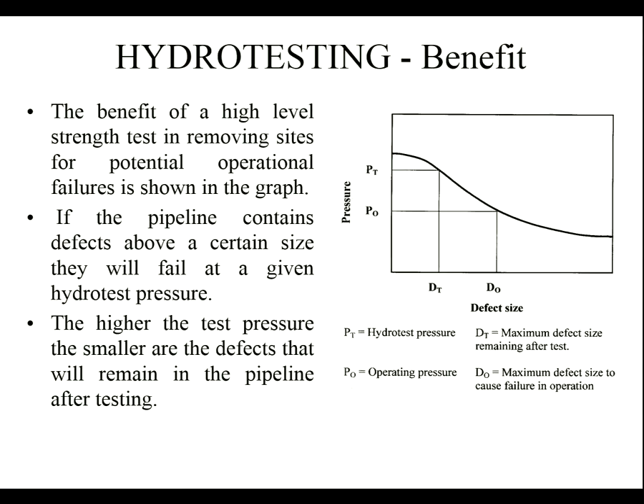And this graph, if you could see all of it, shows the pressure of failure against defect size, and you can see as the defects get bigger, the pressure that you need is smaller. And so P0 would be the operating pressure that you wanted to run at, and PT would be the test pressure. If you run at the test pressure, these small defects will actually fail, and anything bigger than that would actually fail. So hopefully you've got a set of defects in your operating conditions which are much smaller than the defects that would be required to cause failure under those conditions if you do the hydro test correctly.